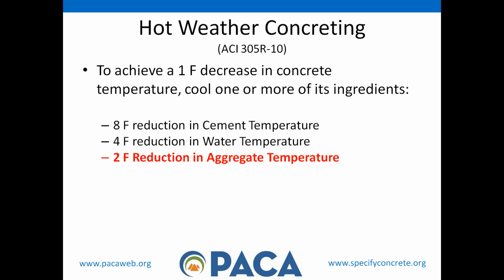To achieve a 1 degree decrease in the concrete temperature, if you cool one or more of these ingredients, you'll see a drastic reduction. If you reduce the cement temperature 8 degrees, you'll get 1 degree concrete temperature. Water temp 4 degrees down, 1 degree. But if you reduce your aggregate temperature 2 degrees, you can get a 1 degree decrease for every 2 degrees of aggregate temp. So that's obviously the biggest bang for your buck.